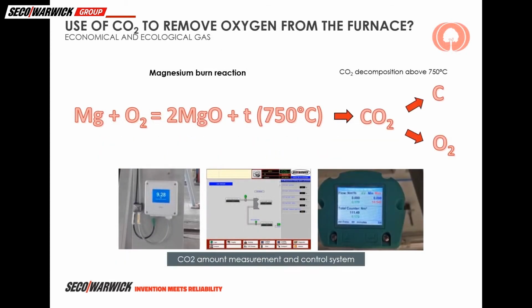This component was carbon dioxide, economical and ecological gas. When the furnace atmosphere oxygen level is reduced by purging with carbon dioxide, there is no risk of magnesium ignition under the safe temperature. However, when magnesium starts to burn and reaches the temperature above 750 C, the reaction of carbon dioxide decomposition starts as well. Carbon dioxide decomposes into carbon monoxide, molecular oxygen, and atomic carbon. Both are escalating the fire.